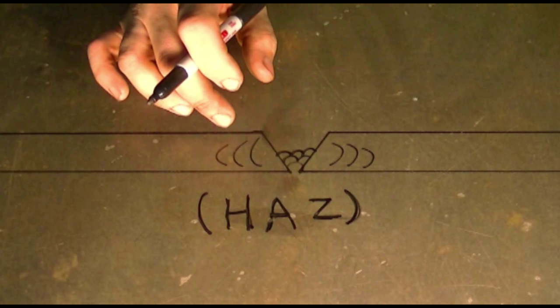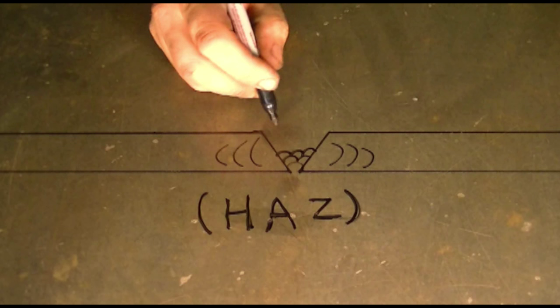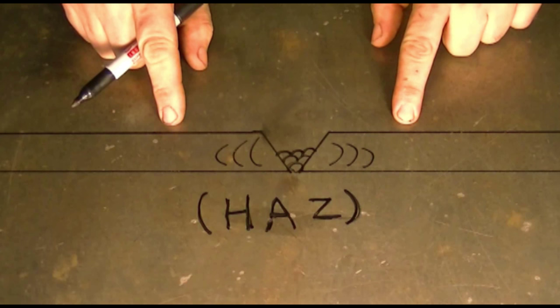You can do things like experience grain growth at high temperature, recrystallization of the steel itself. And recrystallization is exactly what that piece was that I showed you earlier, that grainy structure. And once the metal gets like that, I don't even want to re-weld it. I'll just throw it away and start with a new piece of steel. But as you start building this up, your heat zone is going to get wider and wider. That's why in some welding applications what you'll see happen is people will make a couple of passes, clean up their weld and let it rest. They won't bring it up to a high temperature. They'll actually keep it somewhat temperature controlled. So what else can heat do when you're welding?